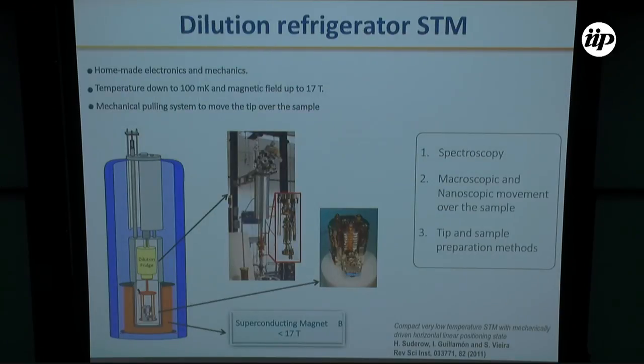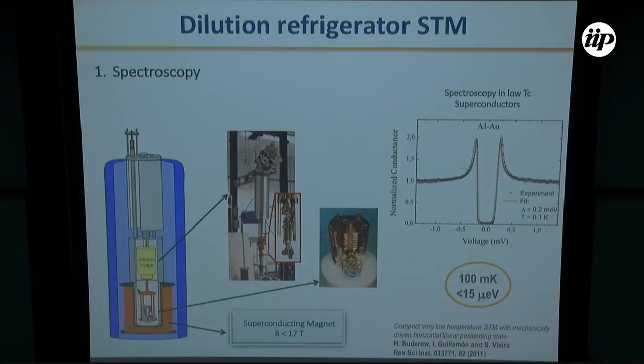Well, in Madrid, we have different dilution refrigerator STMs. So we can cool down to 100 millikelvin and apply magnetic fields up to 17 Tesla. They have an energy resolution of 15 microelectron volts, which has been tested by measuring clean spectra in low Tc superconductors, such as aluminum.